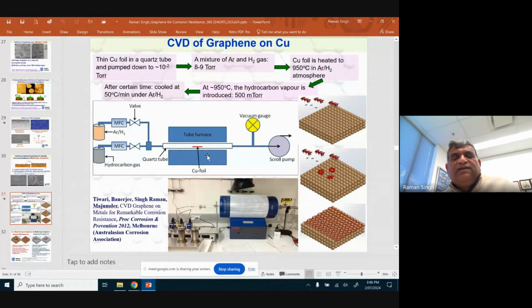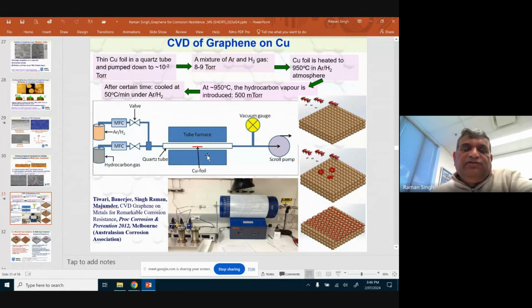If you maintain right partial pressure, you will have graphene. If you don't maintain right partial pressure, you can have diamond, you can have carbon nanotube, you can have carbon soot. So other allotropes of carbon can form. For development of graphene, the partial pressure has to be quite controlled, and that is controlled by very controlled supply of hydrocarbon here. Why copper and nickel? Because both copper and nickel, chemical engineers will know, are very good catalysts for splitting hydrocarbon, and that's what we need.